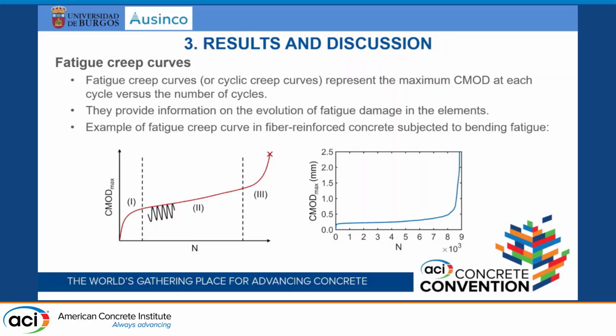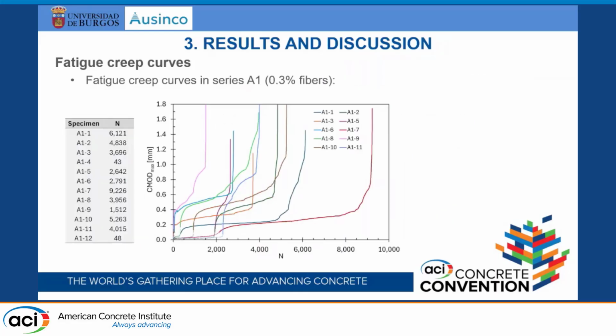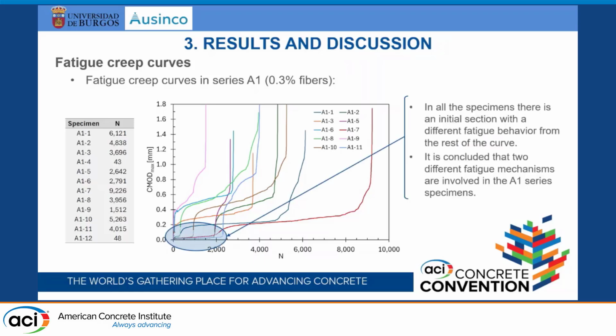And this is also just a real example of what we have. So here we have the fatigue creep curves of the first series with the lowest amount of fibers, only 0.3% of fibers. And what we have found is that there is a double behavior here, because we can see the usual S curves, fatigue creep curves, but there's also a different region with a totally different behavior. What is happening here? What we have found is a primary behavior in uncracked condition. That's what we can find here.